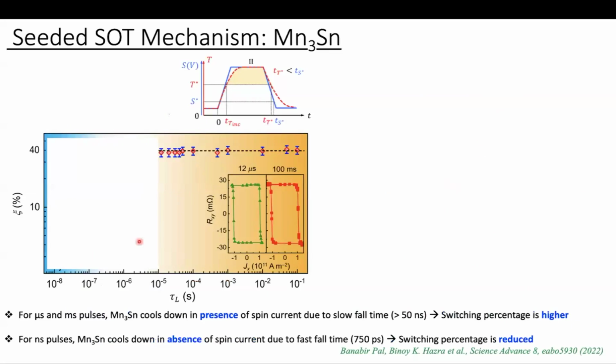Here we performed the pulse width dependence switching experiment. Previously, whatever I showed was for a fixed pulse width, that was a 100 millisecond writing pulse. Now we have changed this. We have varied the pulse width from millisecond to nanosecond.